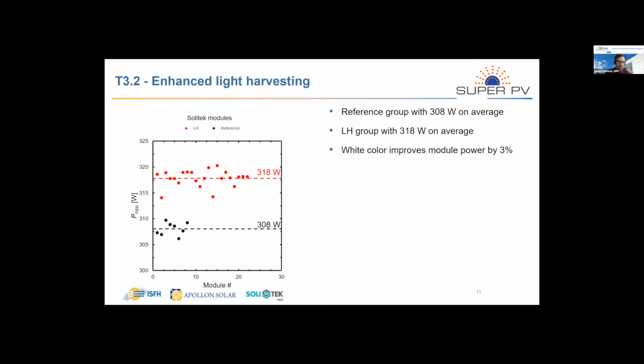And here we have some results for the prototypes manufactured, in this case by Solitech in a mass manufacturing process. This plot here shows the PMPP, so the maximum power for various modules produced by Solitech. The black data shows the reference. So here we have an average module power of 308 watt. And the red data shows the modules employing this light harvesting innovation. And here we have an average module power of 318 watts. So this gives us an improvement with the light harvesting of about 3%.